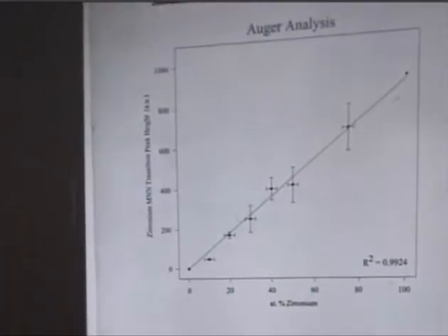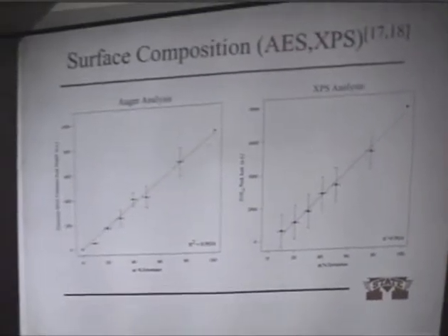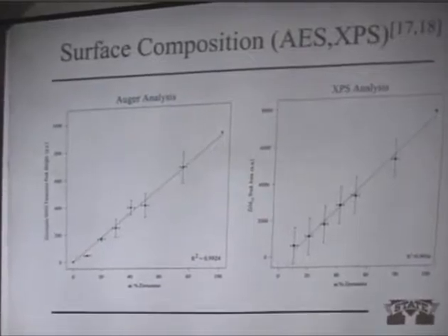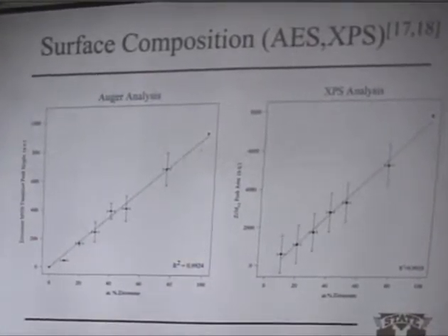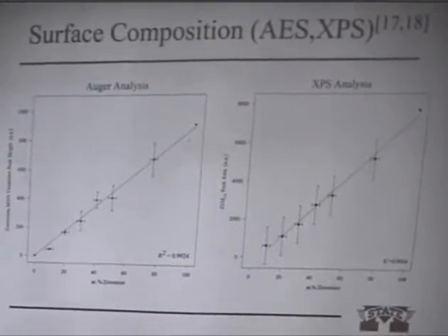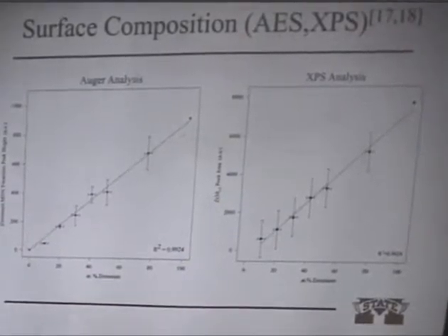The second thing that we wanted to check for was, are we seeing a surface composition that's representative of the bulk? And so the assumption we made here is that if our surface composition is representative of the bulk, we should be able to look at, for example, the zirconia signal measured by Auger or XPS, and it should be directly proportional to the bulk composition. So if we plot the intensity of that signal versus composition, it should be a straight line if we're seeing essentially the same composition at the surface as in the bulk.